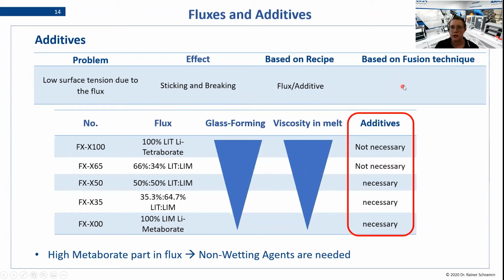And here we can see this is the first time we cannot do anything about it with the fusion technique. We can only tackle this problem with the recipe we are using, and we can either change the flux or we can add an additive. And what we see here is that the more metaborate part will be in your flux, the more it will become necessary to use additives in your preparation. So for high lithium tetraborate parts, it will not be necessary to use additives, but as soon as you are having the same or a higher lithium metaborate part than lithium tetraborate part in your flux, it is very likely that you will need additives to just get a stable, non-sticking and non-breaking bead there.